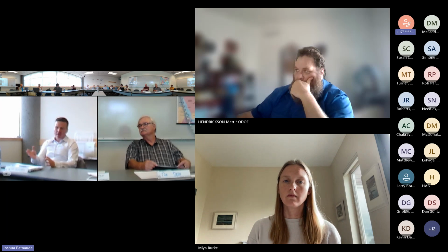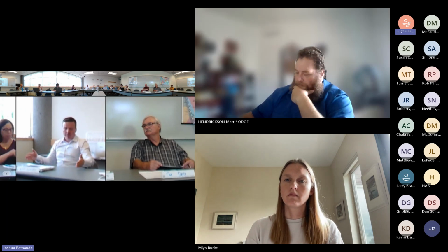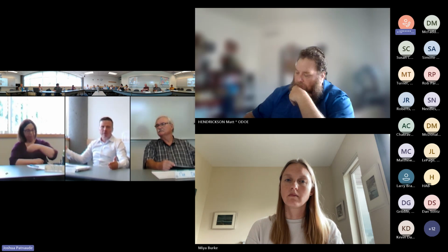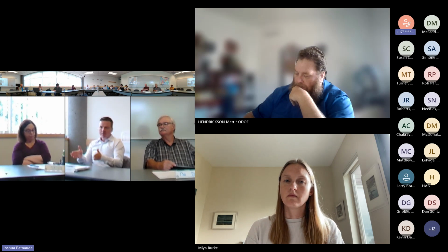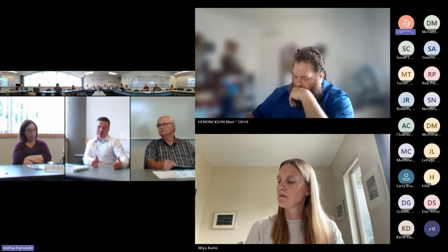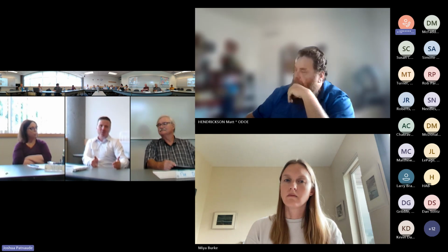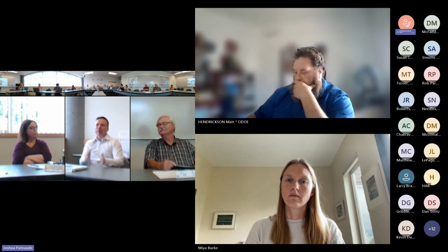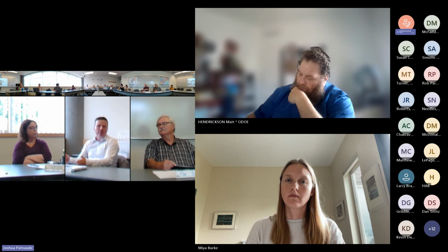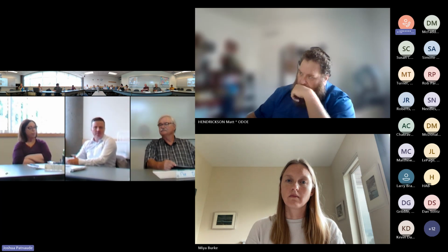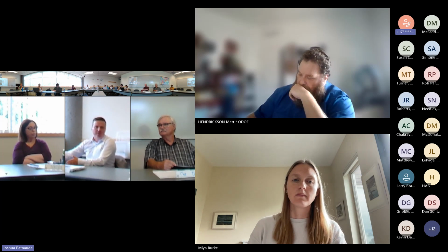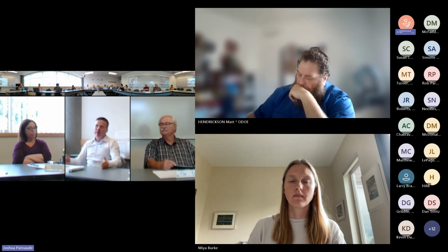Between us and Savannah River over the last 25 years, we've done tests pretty much from 1 molar sodium up to 10 molar sodium. So waste is in the middle. From a retrieval standpoint, if you had to add a ton of water at the end, maybe you get down to that 1 molar. If you put it through an evaporator, you're targeting 5 to 7 molar sodium. And then in the extreme case, you can get it up to 10. So we've studied it across that range.